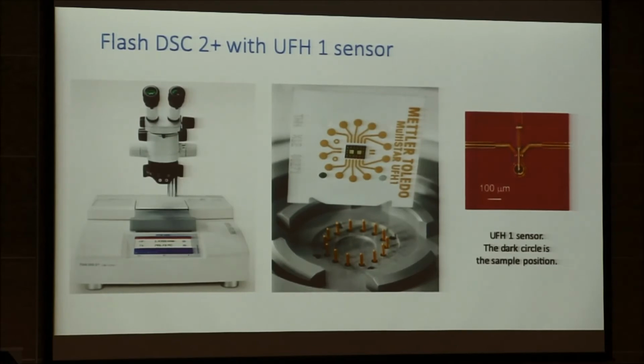10 micron samples means we can go into complex ash, where we have crystals, bubbles, glass, and we can actually pick out a fraction of that by crushing it, and we can extract and isolate a glassy phase of a very fine-grained material, and that opens up all kinds of frontiers for us in determining the thermal history of glasses. The problem with doing a bulk sample of many phases is that often, if it's fine-grained, the glass will react with everything else in it, which is sulfides, oxides. It's a real mess. Volcanoes have the whole periodic table.